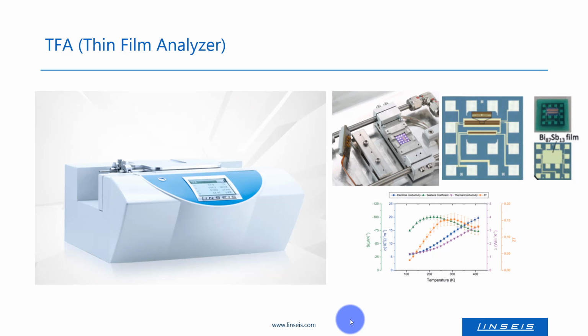The next device we present you today is the TFA, the Thin Film Analyzer. The TFA is a chip-based platform where the chip is a disposable sensor to which the thin layer is directly applied. Furthermore, all sensors and contacts are integrated in the chip. The instrument is built up modular and can not only measure the thermal conductivity in specific heat, but also the electrical conductivity, the Seebeck coefficient, and the Hall constant of a thin film sample.